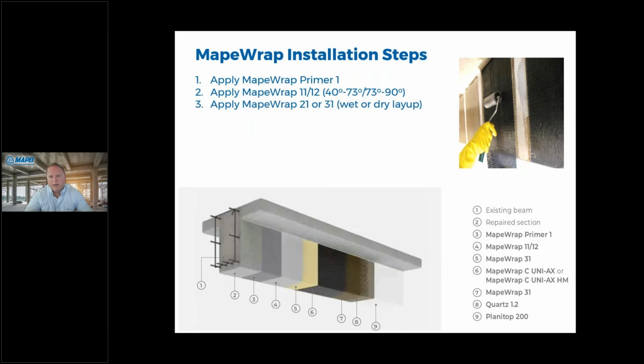I personally kind of cringe a little bit at that because they'll have the saturating resin, and they'll use it to prime the surface. And then if they need to thicken it up, they'll add some fumed silica on site. I'm not a fan of contractors taking the role of a chemist and just adding things into a system that's been formulated and there's been structural engineering calculations behind it. And so at MAPEI, we have these 3 different resin systems to address having the best bond, that's the low viscosity epoxy, having the right adhesive depending on your temperature zone, and then giving the engineer or the contractor options if they want to do a wet or dry layup.